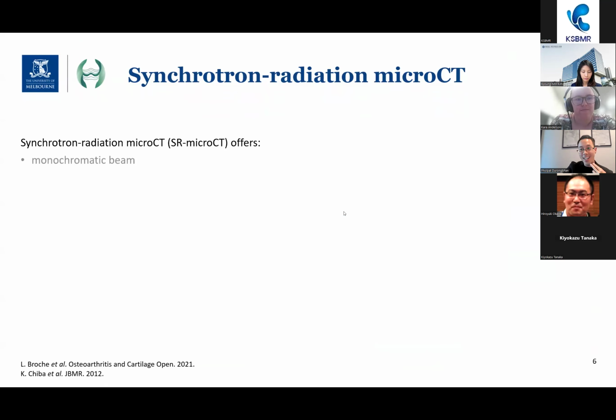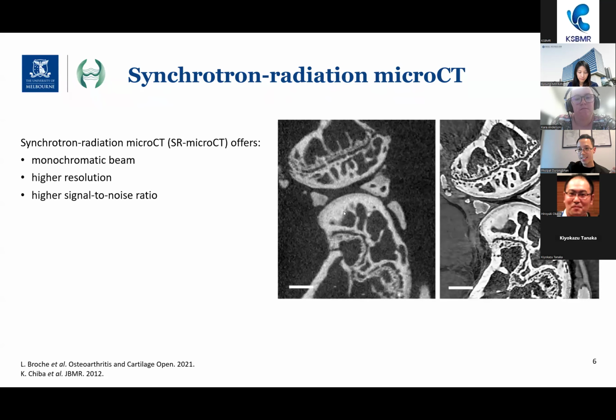So with synchrotron radiation micro-CT, we can get a monochromatic beam. So it's better than your tabletop lab micro-CT systems, and it is better at acquiring different layers of minerals. It can get to nanoscale resolution. It has a higher signal-to-noise ratio, and as you can see in this comparison, a regular micro-CT image is shown on the left, and this is the best the system can do. And on the right is where we use phase contrast synchrotron CT, where you can actually see that low mineral region sitting on top in the joint space area.